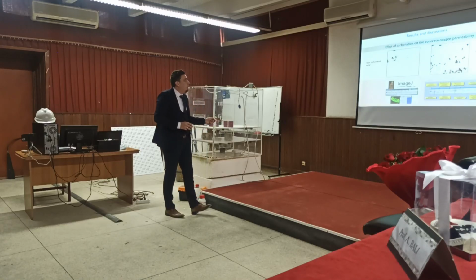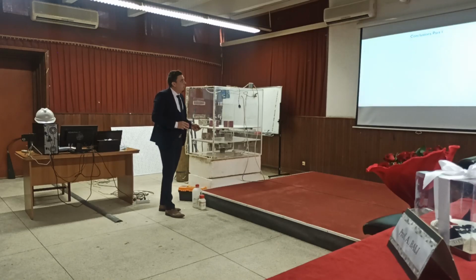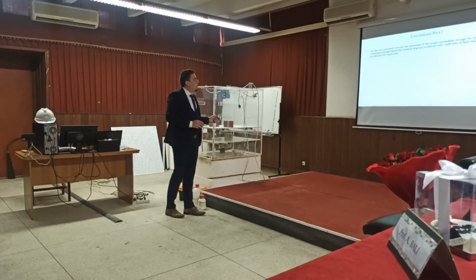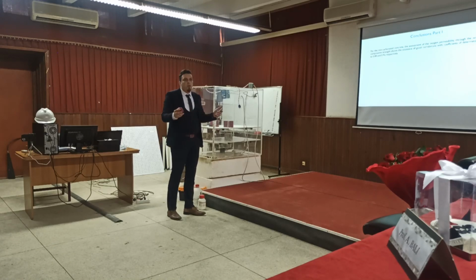And we found that with the image, we can generate binary images in order to calculate the porosity. And you see here that in the carbonated zone, the black points, which are the porosity, are much higher than in the non-carbonated zone. Arriving at the conclusions of part 1, we found that for the non-carbonated concrete, the assessment of the oxygen permeability through the w/c ratio and compressive strength shows the existence of good relations.